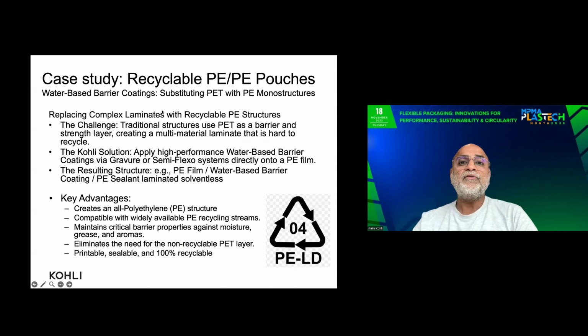Case study here, we are trying to substitute PET material with PE material. So basically, we are producing a material which has to have a similar barrier strength and similar performance. The advantage was to create an all polyethylene PE structure, which is compatible today with widely available recycling streams in the world. It is maintaining critical barrier properties against moisture, grease, and aromas. It's eliminating the need for the non-recyclable polyester material, and it's easily printable, sealable, and 100% recyclable.